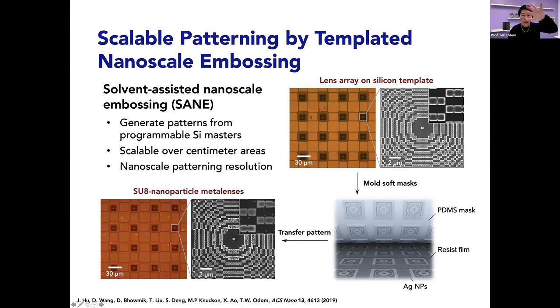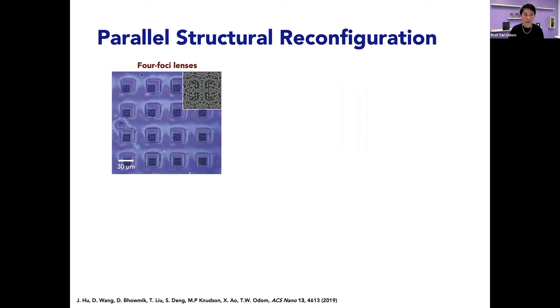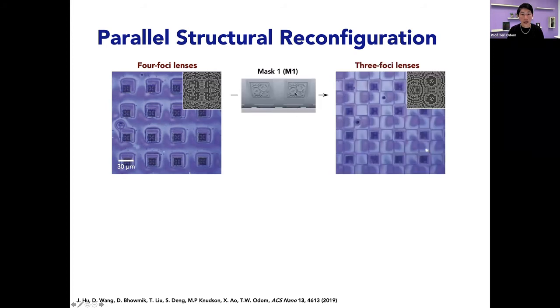So all of these metalenses, these patches, are still on top of the plasmonic array. So we can take this mold, and then we can wet it with solvents and put these different patterns up for drying. We can then take a different mask, wet it with solvent, and retake all of this polymer for the 4 focal point lenses, and then make 3 focal point lenses. And then this process can be just repeated.